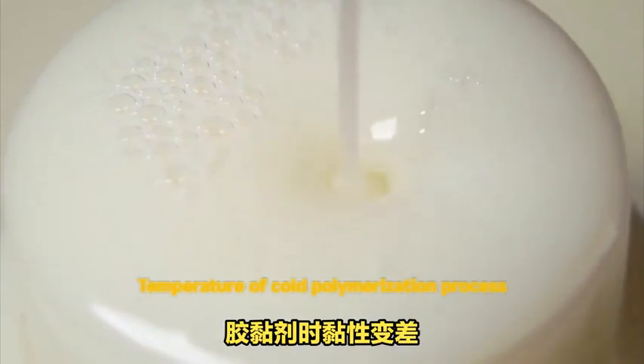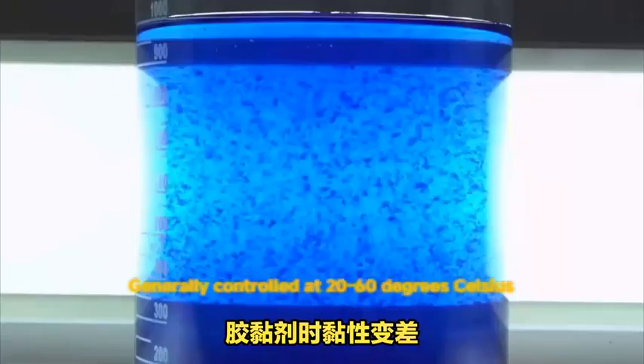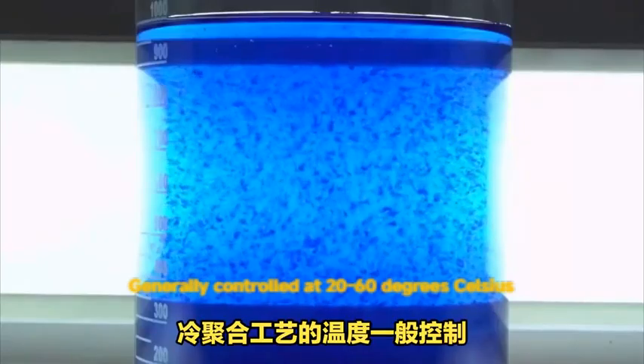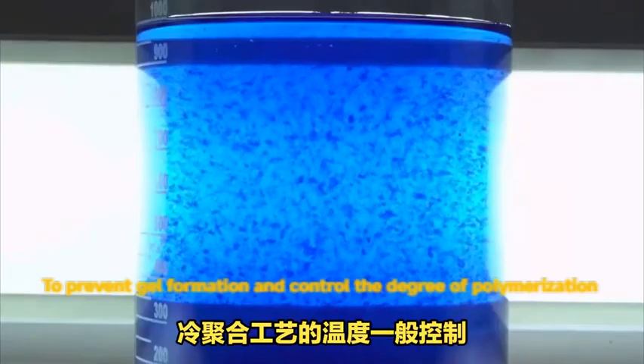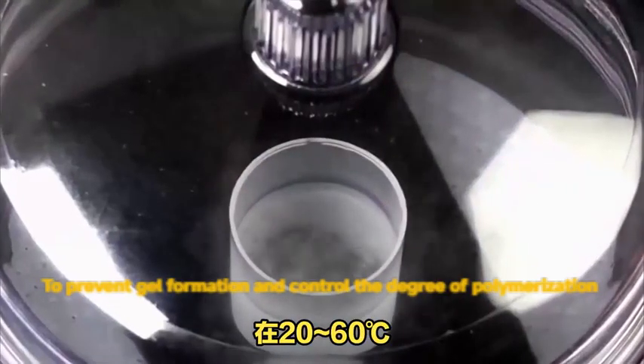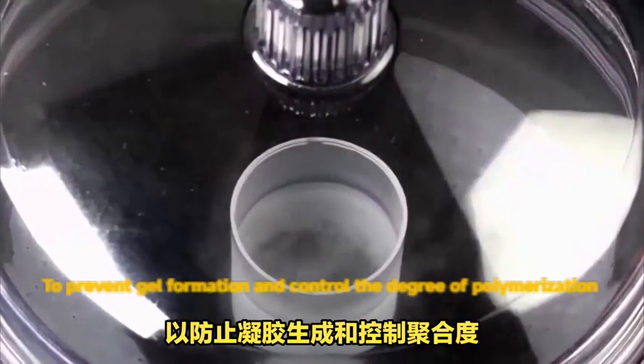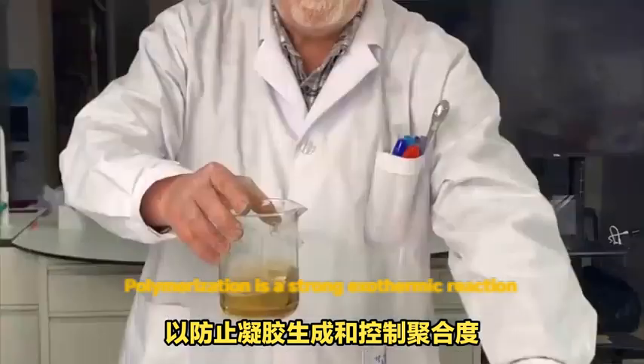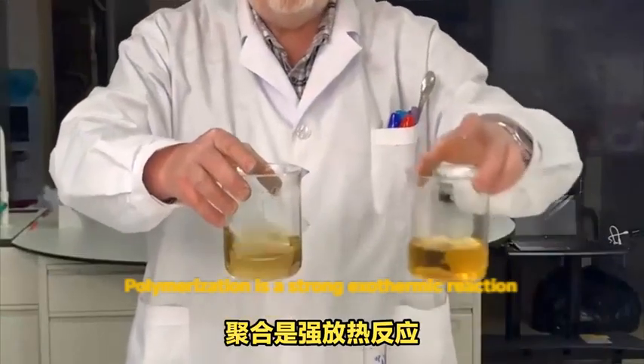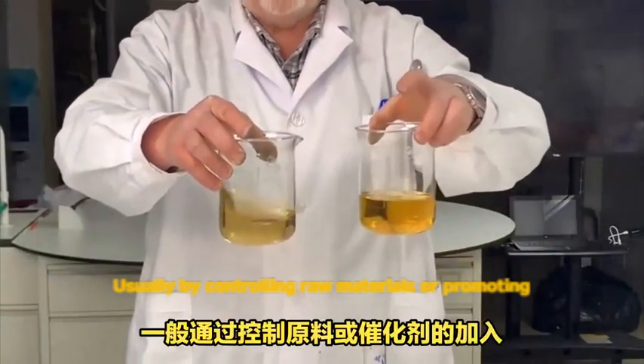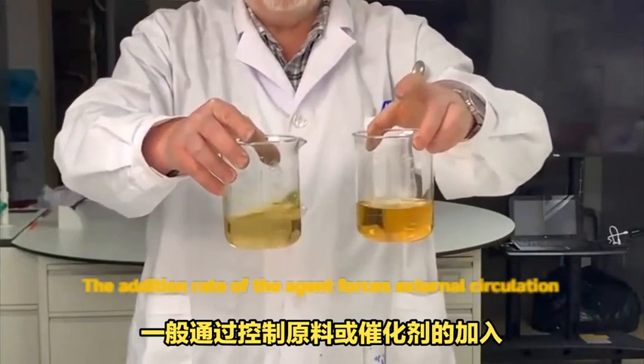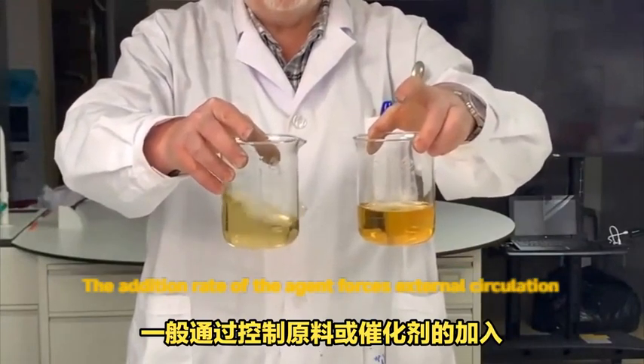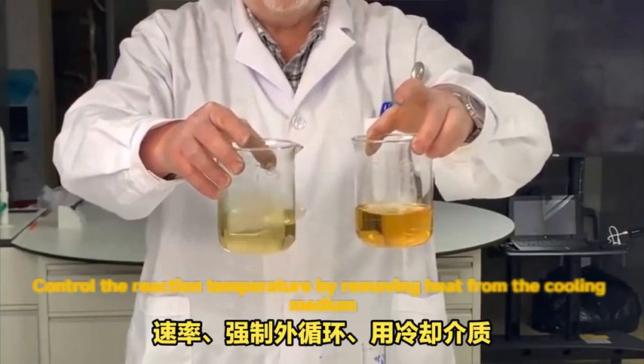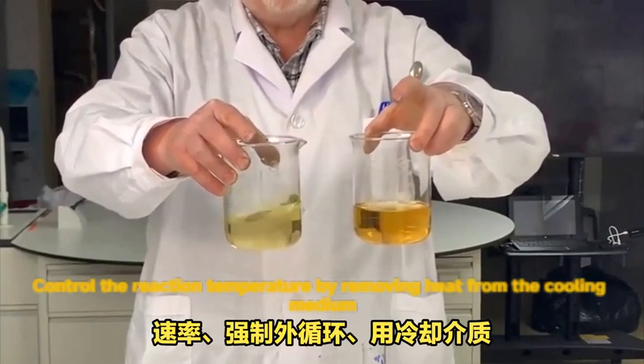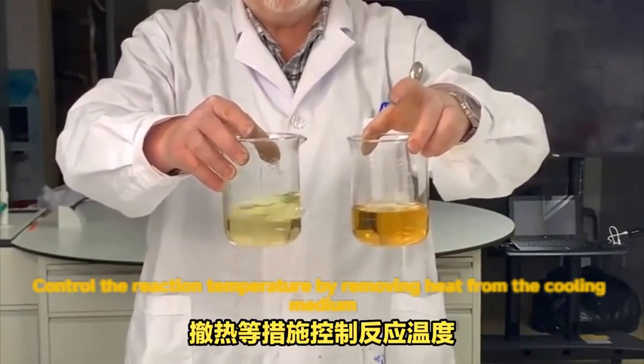The temperature of the cold polymerization process is generally controlled at 20 to 60 degrees Celsius, to prevent gel formation and control the degree of polymerization. Polymerization is a strongly exothermic reaction, usually controlled by the addition rate of raw materials or promoter, and by forced external circulation. The reaction temperature is controlled by removing heat with a cooling medium.